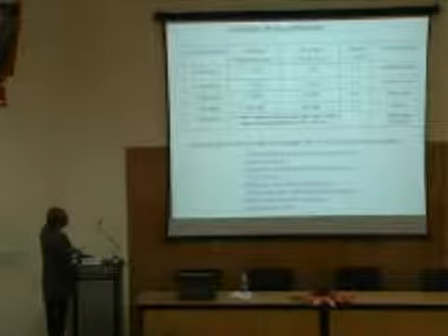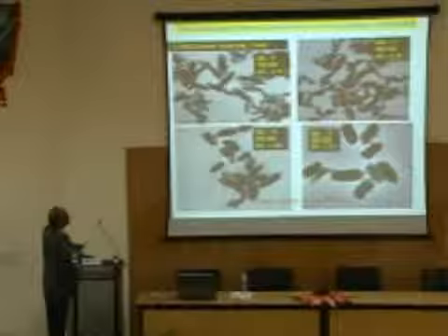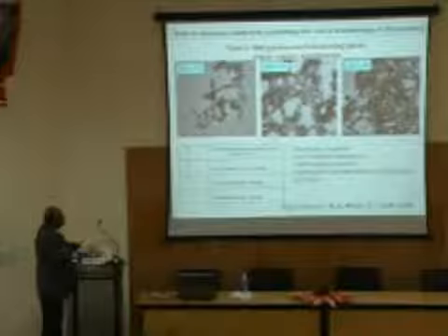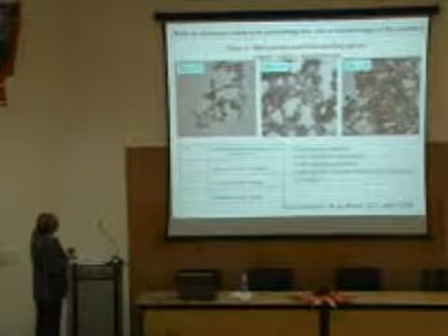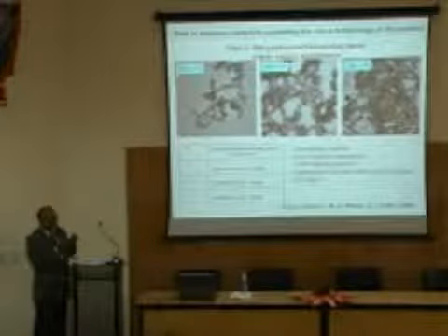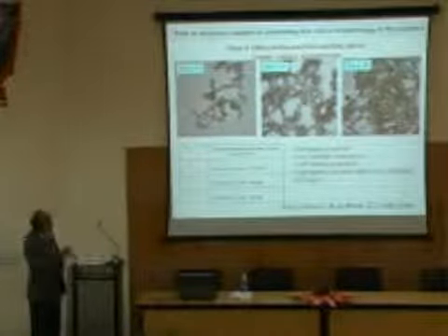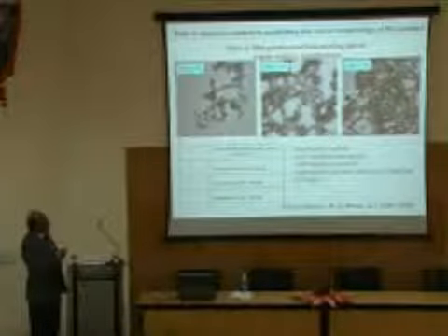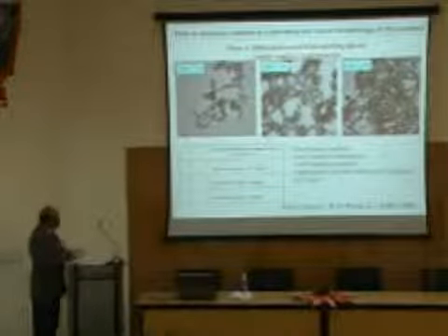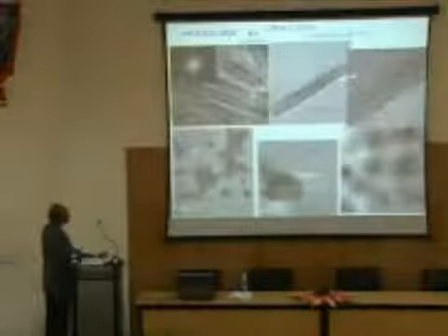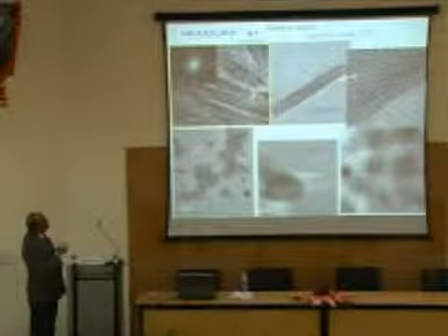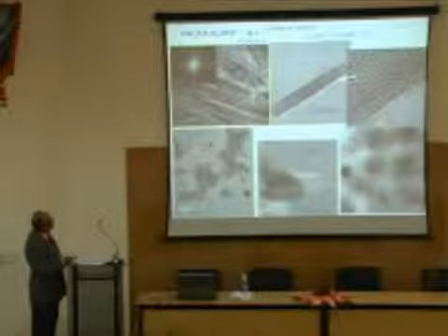Okay. So this is similar things, so I will not go into that. Okay. This is again, if you change the water content, that means those spheres you are making, how much water is there. If you control the amount of water inside, which is called the W naught parameter, 11, 14, 16, you can change the size of the particles. Okay? So that also we have done, right? Okay. Now this is another type of rods. You can see the difference in the two rods.